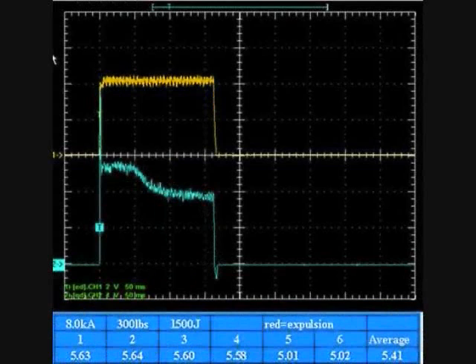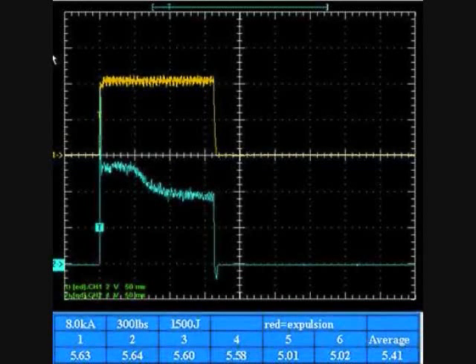The second waveform, the top is still the current, the green color one is the voltage. And I'm still welding 300 pound, 8 kiloampere, except this time I adjust the energy to 1,500 joules. You can tell the weld time is longer. And out of the 2 coupons, 6 welds, the average is 5.41 millimeter. Since this is measured, I can be sure I'm right.